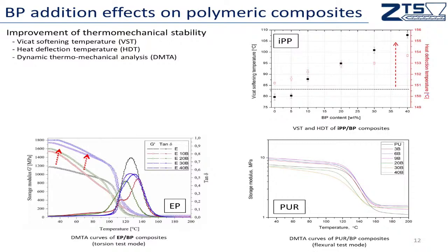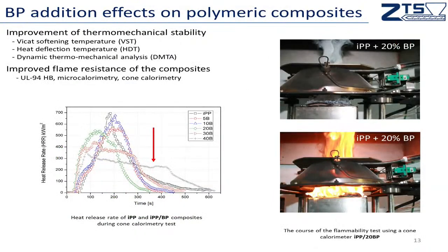And when we move to the next slide, we can see another property which is extremely important from the application point of view. The biggest weakness of the polymers is their low thermal stability and high flammability in comparison to metals or ceramics. So we prepared wide studies of the flammability, of how materials behave in fire conditions. And here we can see the polypropylene composite samples with 20% of the basalt powder during the course of the cone calorimetry test, which is the most commonly used method for determination of the fire behavior of materials.